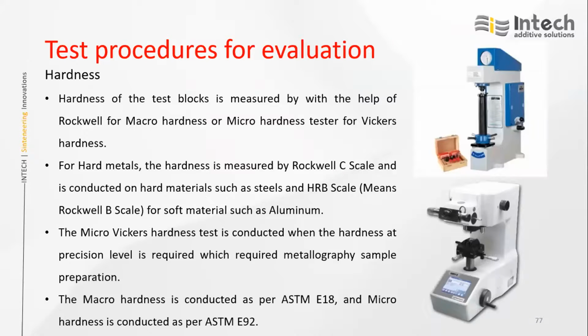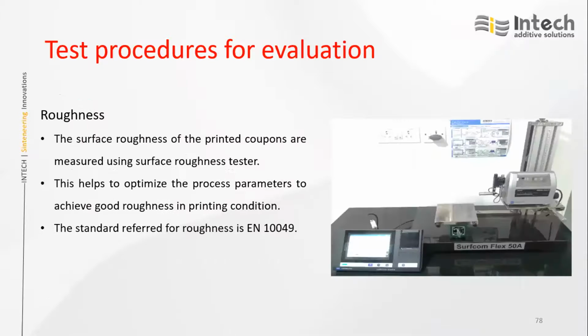For hardness, if it is a printed coupon and you directly want to check on the coupon, we will do macro hardness. And if you want to check along the grain boundaries at a finer level, then we can do micro hardness.